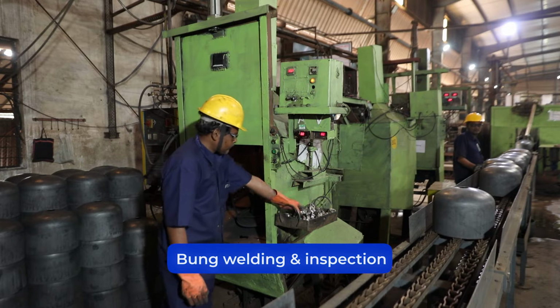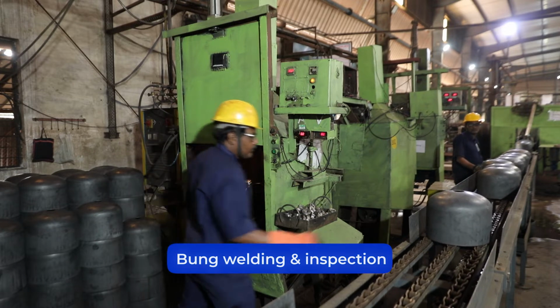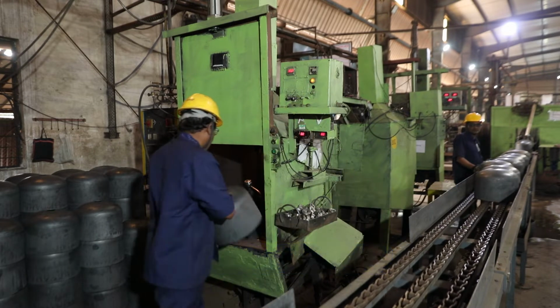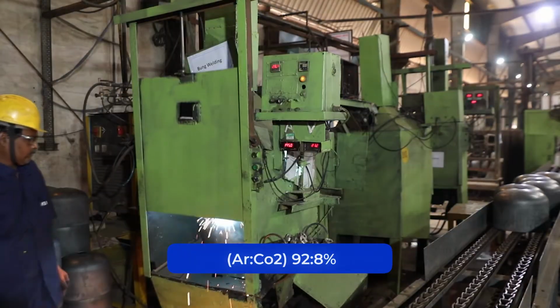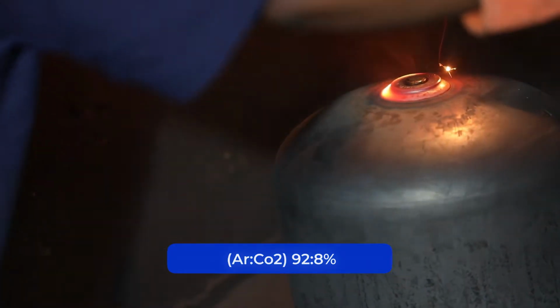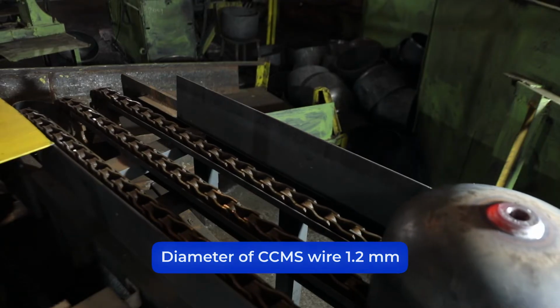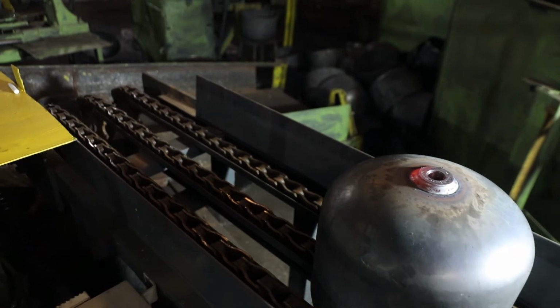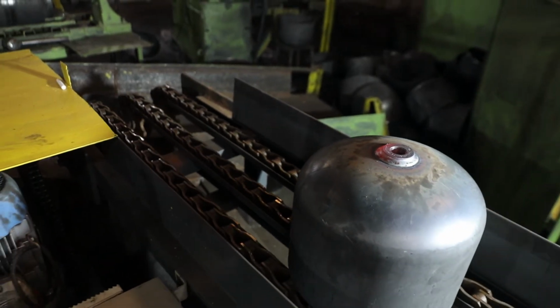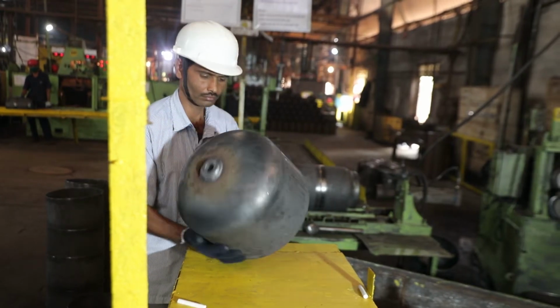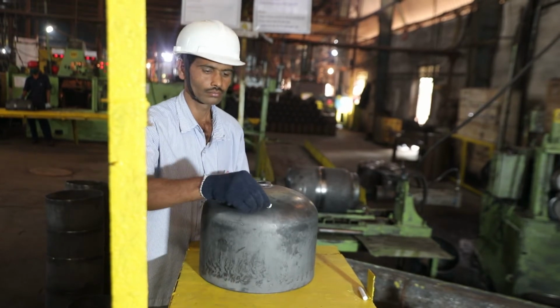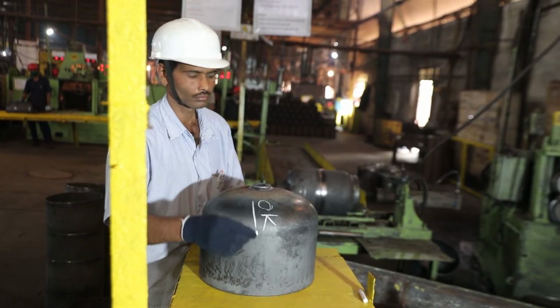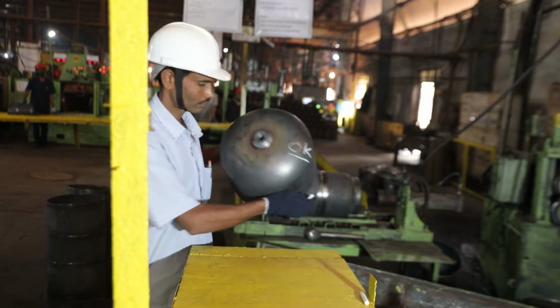Now for bung welding of upper halves. It will be done by metal inert gas welding process with argon 92% and carbon dioxide 8%. Diameter of the copper-coated mild steel wire will be 1.2 mm. A bung weld inspection should be carried out to find defects like pinhole, blowholes, undercut, incomplete welding, burnout and welding profile.